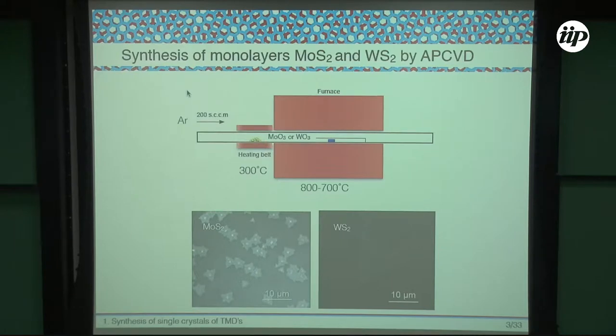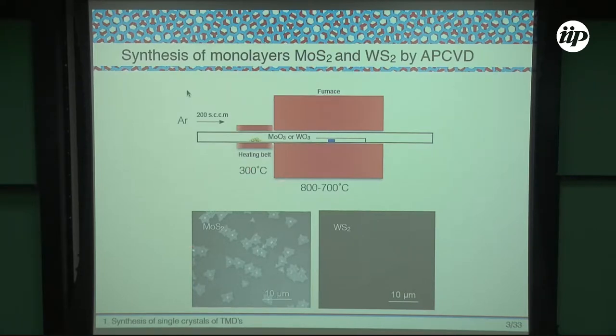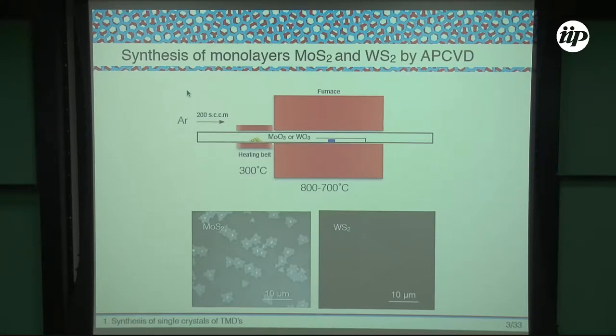On the left side, you can use another furnace or a simple heating belt, because the temperature there is just 300 degrees Celsius. At the center, you have a quartz tube. Inside this tube, on the left side of the heating belt, you put the chalcogenide — that could be sulfur, selenium, or tellurium. In the middle of the furnace, we put the precursors. If you want to grow molybdenum disulfide, the precursor is the molybdenum oxide; for tungsten disulfide, the precursor is tungsten oxide.